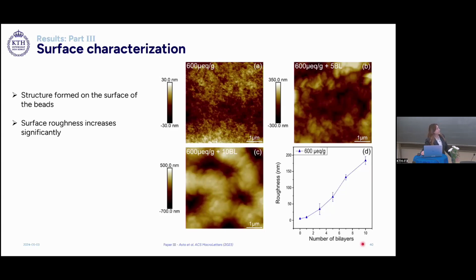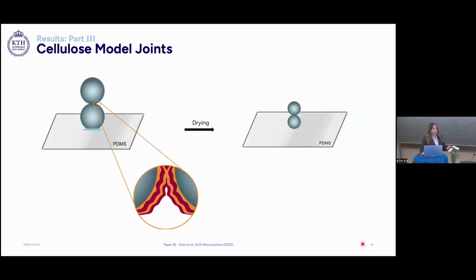And these structures formed on the surface will affect how these surfaces will come together and dry. To be able to study this, we created a model joint using cellulose beads by drying two cellulose beads together. One of the advantages of using the beads as a model material is their spherical shape, which allows us to visualize the contact area before separation.